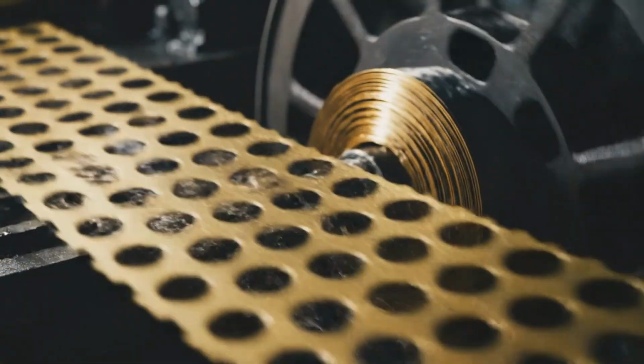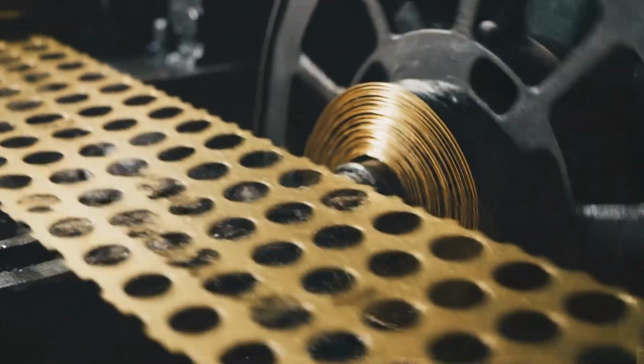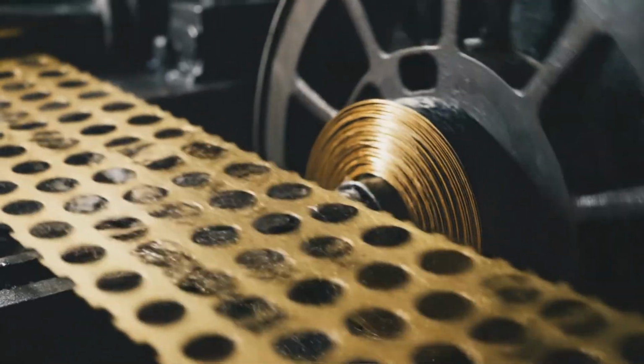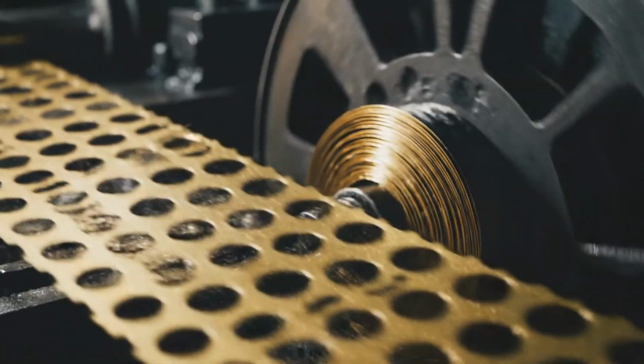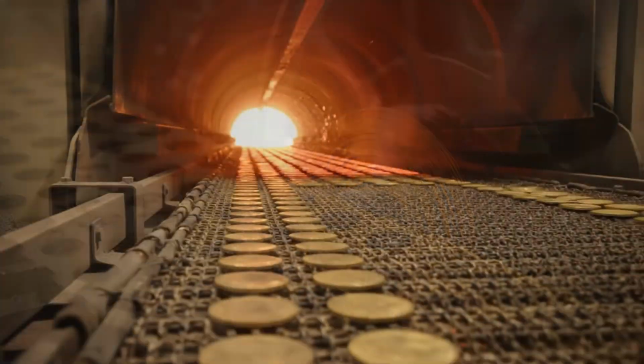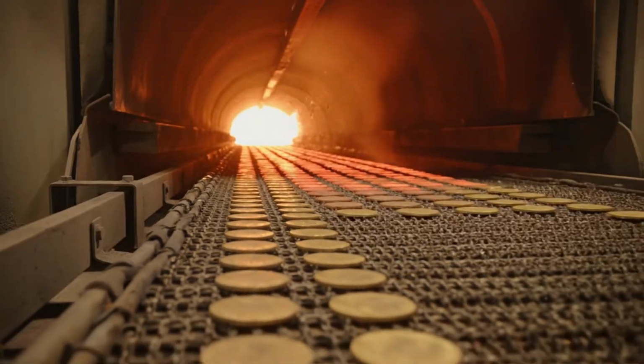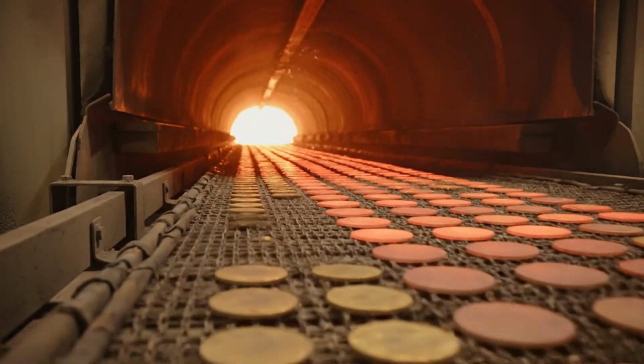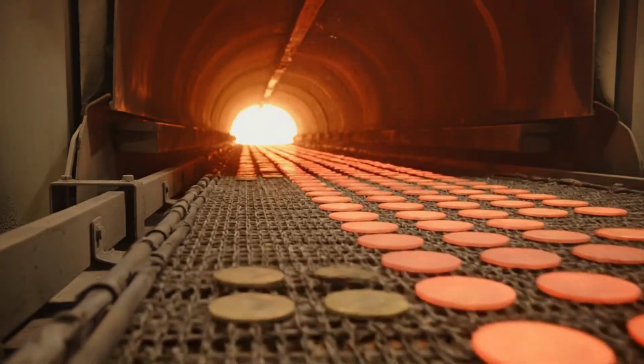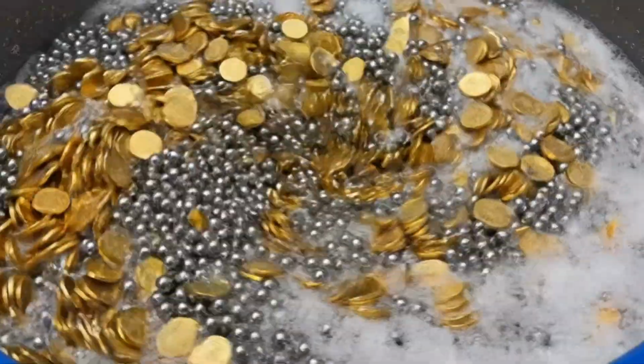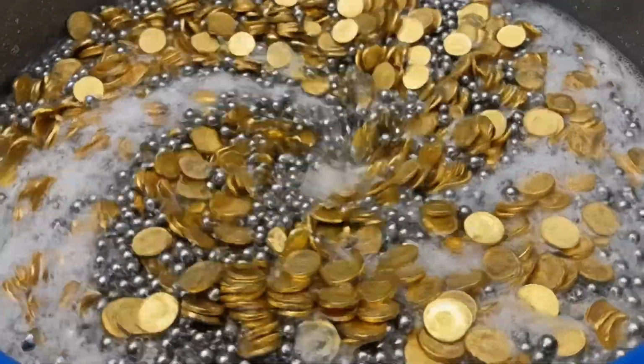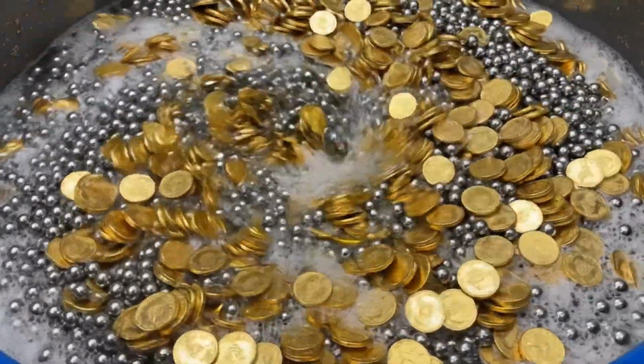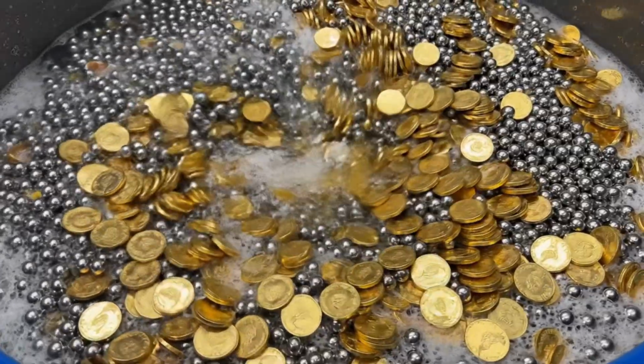The leftover webbing is immediately collected and sent back to the furnace, as our closed-loop system ensures absolutely zero waste of this expensive raw material. These blank discs are currently too hard for striking, so they enter an annealing oven to soften the crystal structure for the detailed stamping process. After heating, they are tumbled in a cleaning solution with small steel bearings burnishing the surface until each blank shines with a distinctive bright luster.